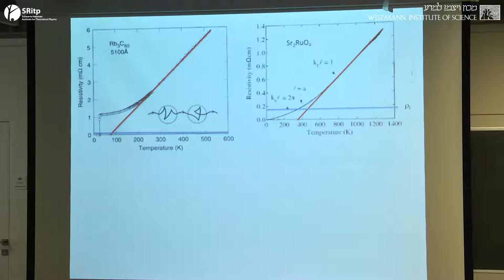This is the real strontium ruthenate. This is data from Andy McKenzie. And again, you see this failure to saturate. Here, at low temperature, this system becomes a nice Fermi liquid. There's no problem with this low temperature behavior. There's some sort of crossover that occurs as you cross this line, and the temperature dependence crosses over from T squared to T. So it tells you that it's doing something new. So that's, of course, good. But this, again, is not explicable by Boltzmann transport theory.